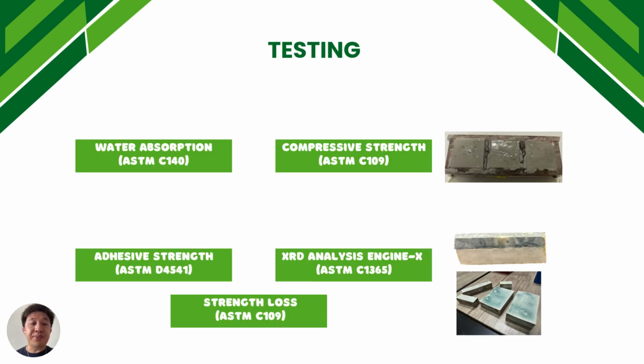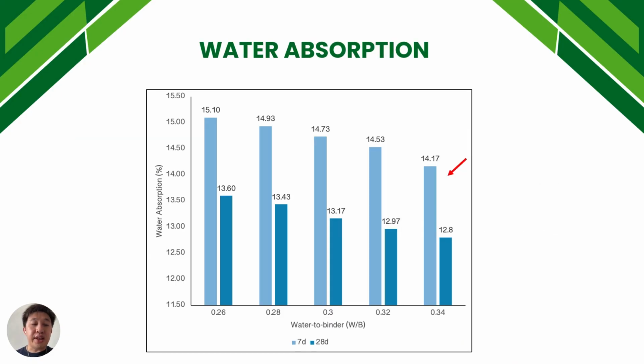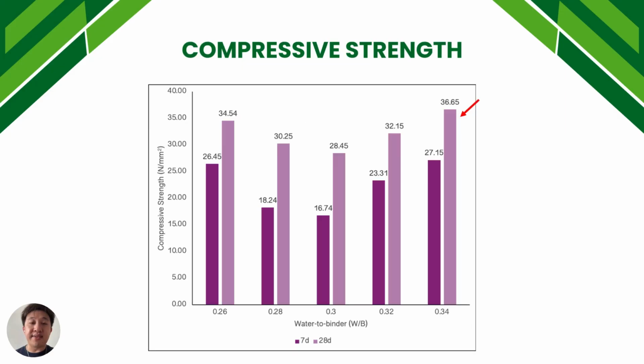The testing we have carried out is water absorption, compressive strength, and adhesive strength, as well as the analysis using Engin-X, and strength loss. For water absorption, the water to binder ratio of 0.34 has the lowest, which is 14.17% at 7 days and 12.8% at 28 days. For compressive strength, it was also found that the water to binder ratio of 0.34 has the highest compressive strength, which is 27.15 megapascal at 7 days and 36.65 megapascal at 28 days.